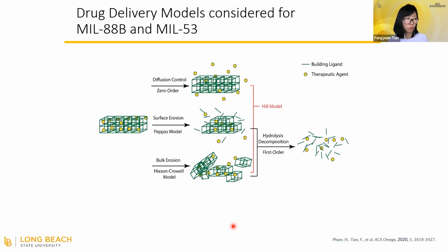But when we look at the drug releasing process, we found that it could go through different models. For example, the drug molecules will just release out from the framework without changing the structure. This is known as diffusion control releasing. Or the material will start decomposing, but starting from the surface. This is a surface erosion process. In that case, they should follow a Peppas model. Or the crystal can break down into smaller pieces and release drugs from itself. That's known as bulk erosion.